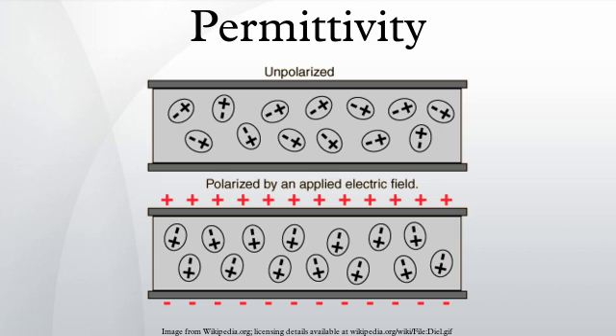Moreover, the fact that the polarization can only depend on the electric field at previous times, chi equals zero for t less than zero, a consequence of causality, imposes Kramers-Kronig constraints on the susceptibility chi(omega). As opposed to the response of a vacuum, the response of normal materials to external fields generally depends on the frequency of the field. This frequency dependence reflects the fact that a material's polarization does not respond instantaneously to an applied field. The response must always be causal, which can be represented by a phase difference. For this reason, permittivity is often treated as a complex function of the frequency of the applied field omega. The definition of permittivity therefore becomes complex, where D_0 and E_0 are the amplitudes of the displacement and electric fields, respectively, i is the imaginary unit, i^2 equals -1.